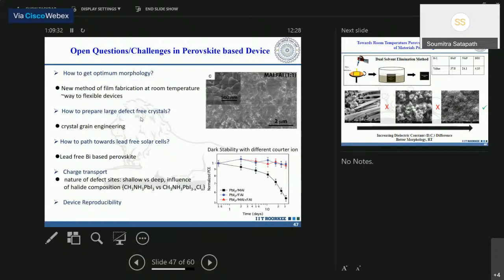In the very beginning, when I was discussing the silicon solar cell, I said that one of the main reasons for efficiency loss in a cell is the loss that comes from defects or traps. Defects at the boundary, defects at the interface, defects at the metal-semiconductor interface. Now, when I similarly grow the perovskite crystal, there can be impurity and imperfection. The impurity or imperfection gives me the defect or trap.